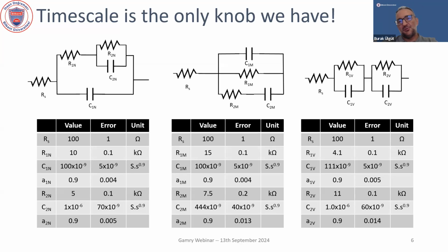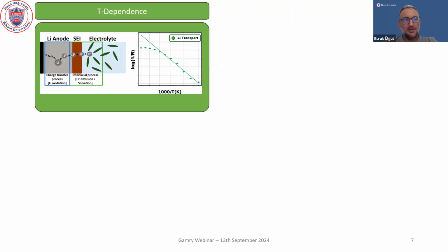So what I'm going to talk about for the rest of my talk is three ways in my group we are trying to do this disambiguation. Number one is the use of temperature. We can look at temperature dependence of impedance spectra. And the temperature dependence clearly helps us identify which data feature belongs to which electrochemical process, whether it's activated, whether it's transport, kinetics, what the activation energies are, and we can correlate that with other experiments in order to match features in the data to electrochemical processes inside the batteries.